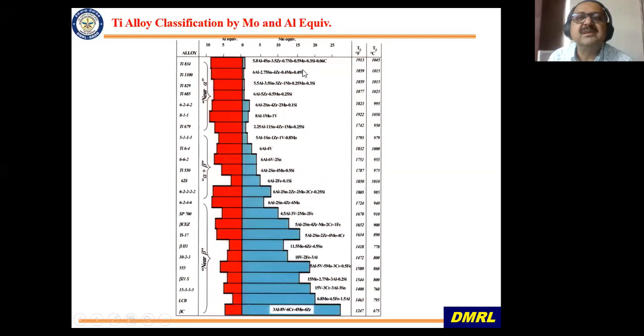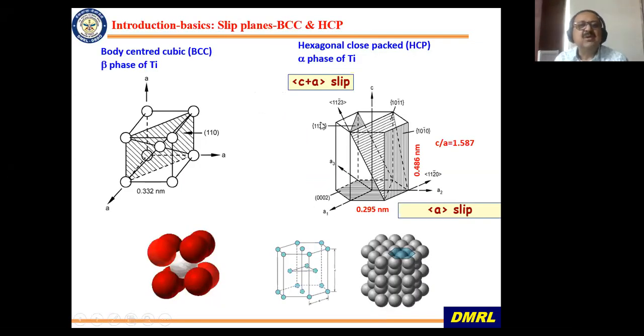And if you look at the beta transus temperatures of these alloys, that is near alpha alloys, they are higher, and if you look at the beta transus temperature of the beta alloys, they are much lower, because you have higher amount of beta stabilizer in there. Now coming back to a bit of basics before I go on to the properties, etc.